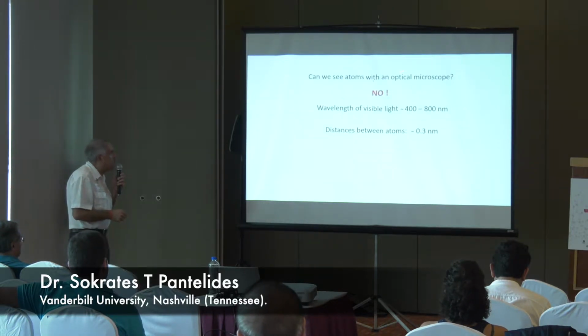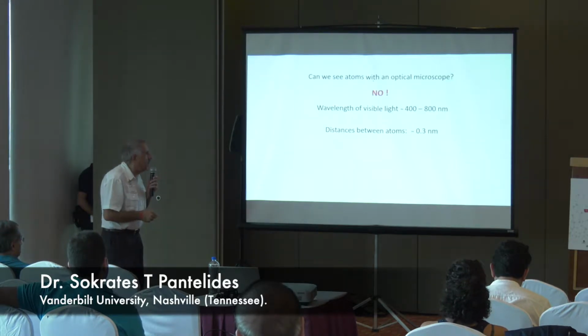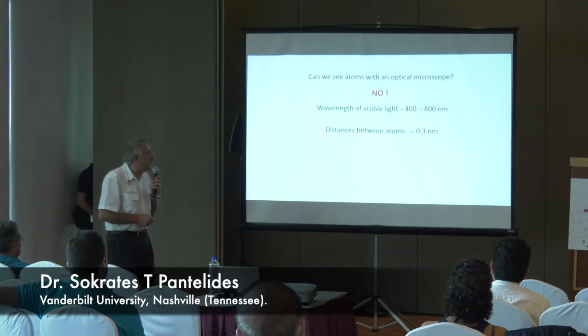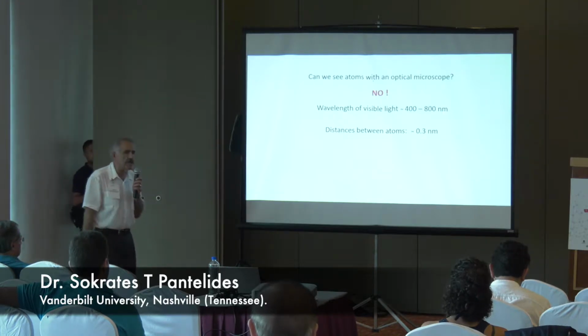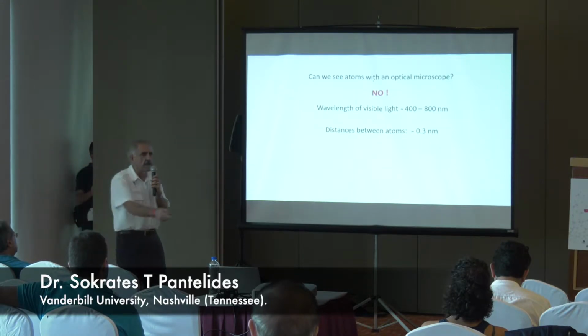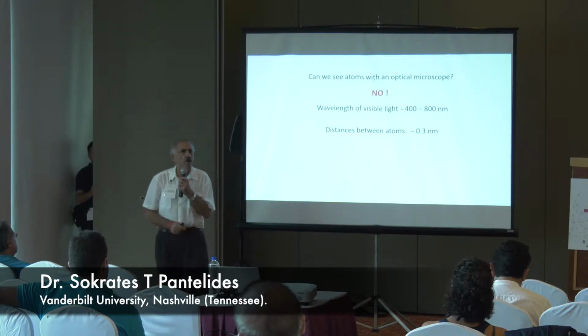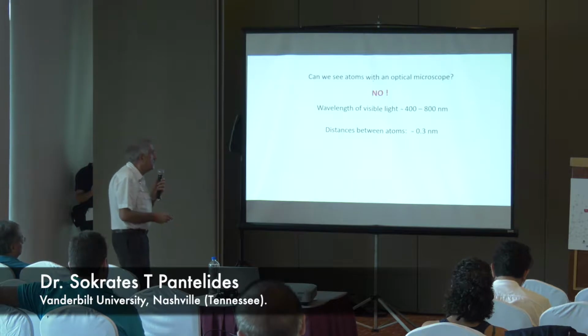And the question is, can we see atoms with an optical microscope? And the answer is no. The key is the wavelength of visible light is about 400 to 800 nanometers, but the distances between atoms are 1/3 or so of a nanometer. And the wavelength of light, if it's very big, and you are trying to see this small thing, you are not going to resolve it. You need wavelengths on that scale.